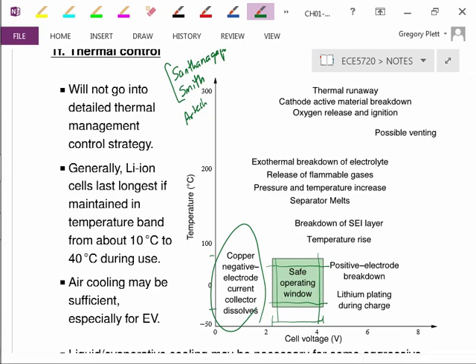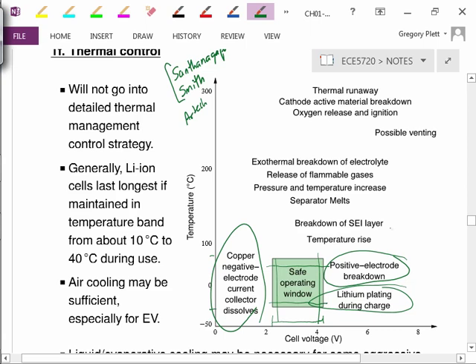At high voltages and low temperatures, we start lithium plating during charge. I've mentioned that before a number of times. So that's not a good thing either. You lose capacity relatively quickly. We have dendrites forming, again, possibilities of short circuits. At high voltages and high temperatures, the positive electrode active materials can actually start dissolving into the electrolyte, and you start losing capacity. And the chemical constituents of the positive electrode can try to cycle like lithium does and end up contaminating the negative electrode and so forth. So that's bad. We want to stay away from too high voltages.